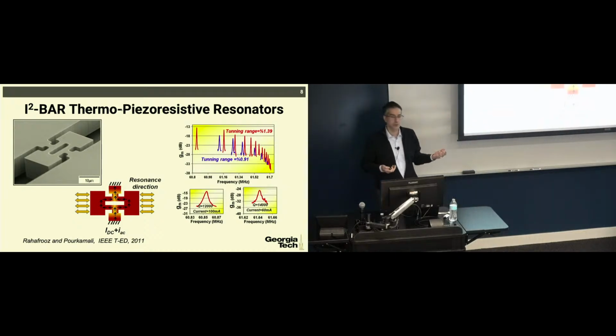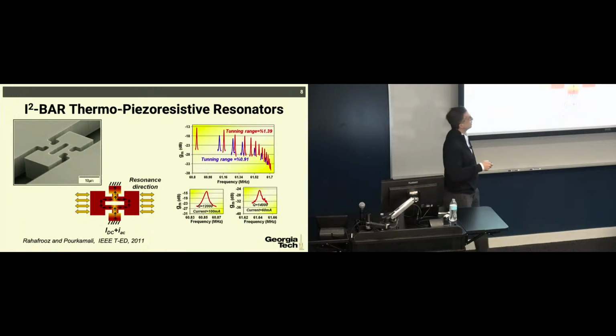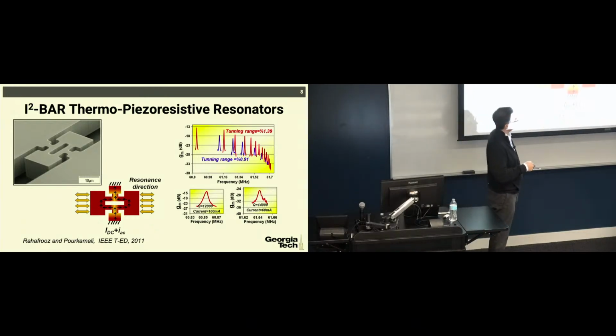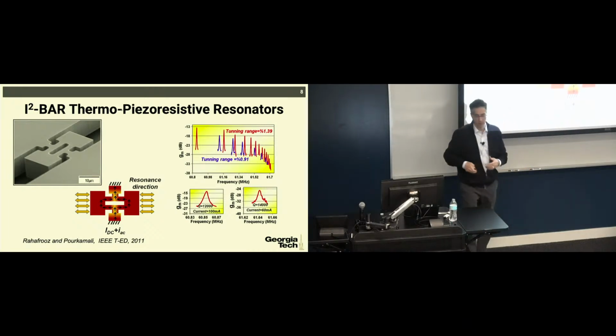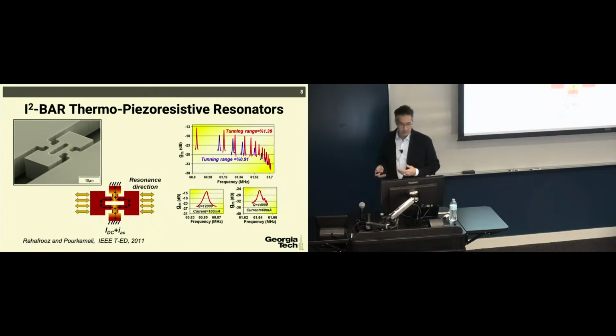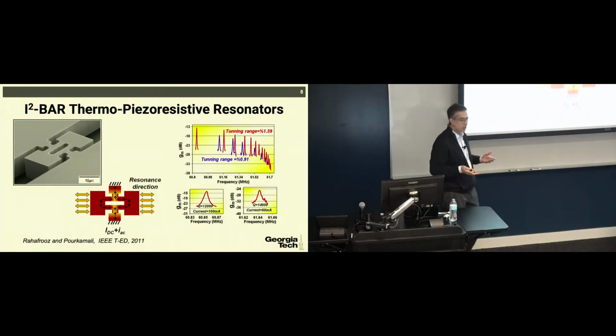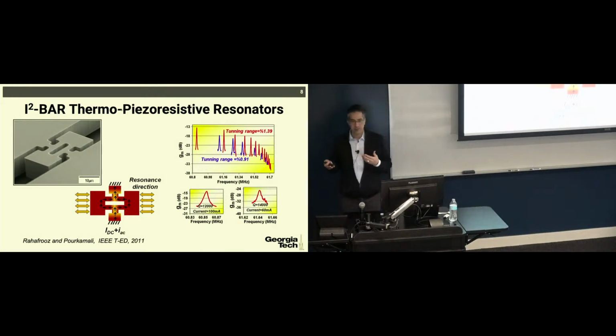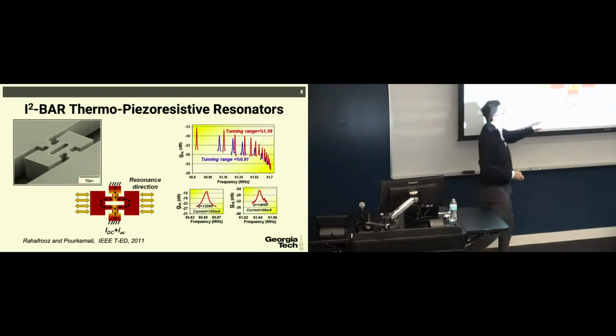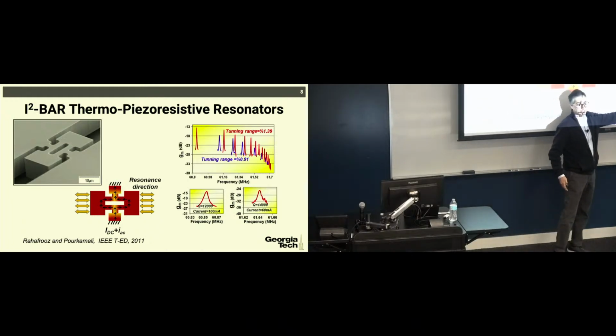So that's the piezo-resistive effect. By just running a current, you see these nice resonance peaks out of the device. Qs are in the order of 12,000 and 14,000. Now, a lot of people asked back then, thermal actuation, isn't it going to be slow? Because people have a hard time imagining that things can heat up and cool down in the matter of nanoseconds. And look at the frequency of this device. This was a 60 megahertz device.